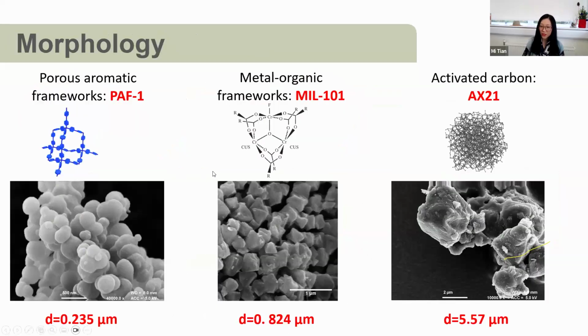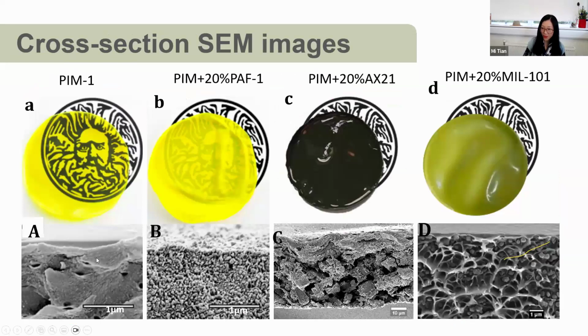So these are morphologies of PAF-1 MOF and activated carbon. We can see they have different density and particle size. From the cross section of the membranes, we can see the MOFs, because of the density and the crystal size, are distributed homogeneously in the PIM1 matrix.